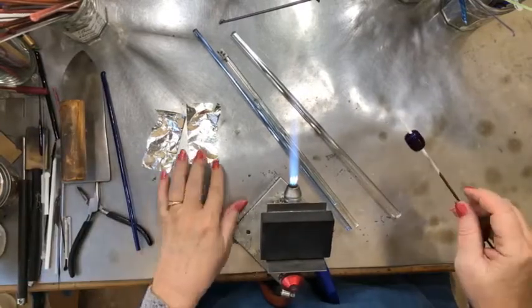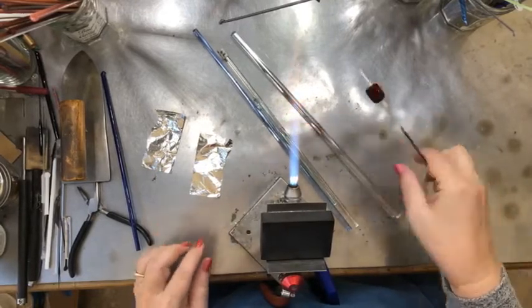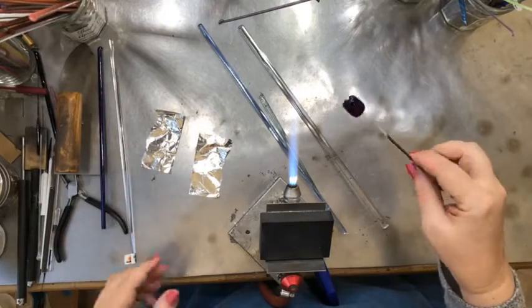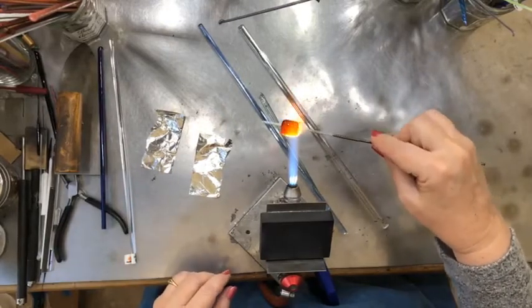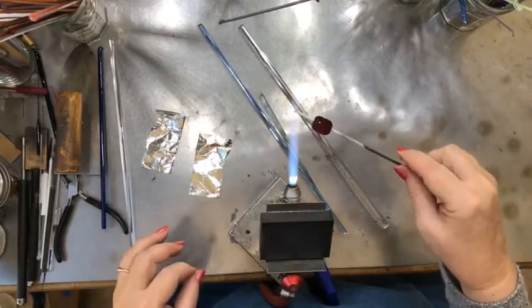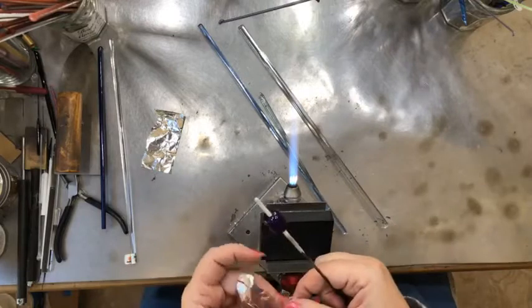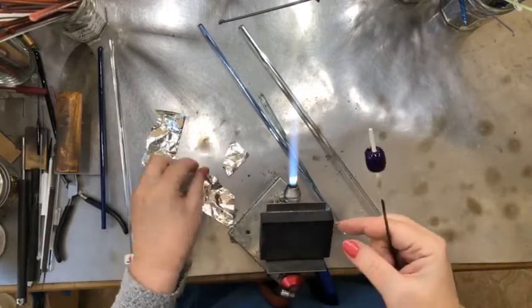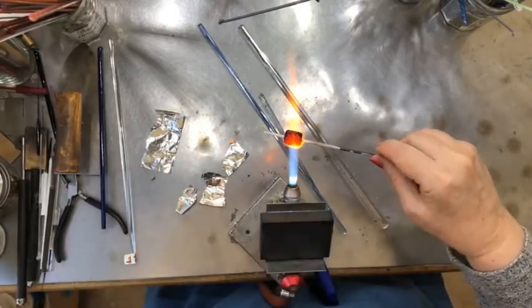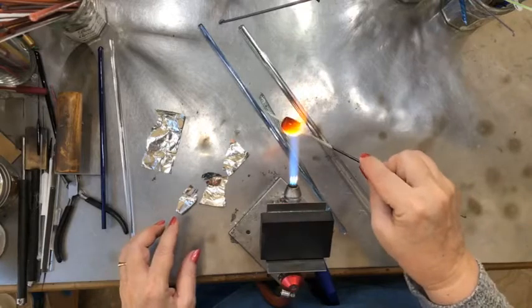What I want to do is heat up the base bead and then lay the silver over the top — I'm not going to put it into the flame. I'm going to heat up my clear and put it over the silver, and you're going to melt some of the silver in and you just can't help it. That's okay. You won't have silver covering it 100%. The smaller the pieces you put on that you can cover immediately, the easier it will be. Let's tear off a couple of pieces — you can always add a little more on. I want to heat this up but I don't want it red hot so that the silver melts on contact.